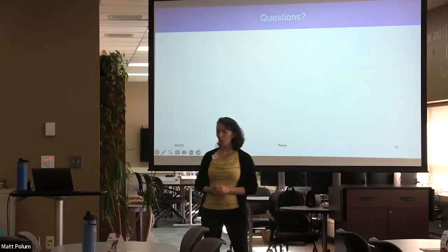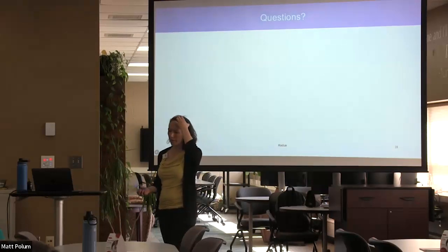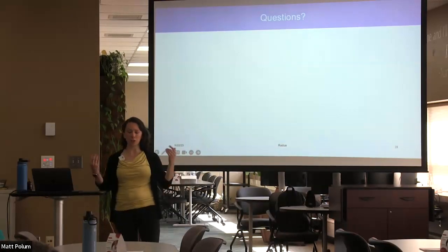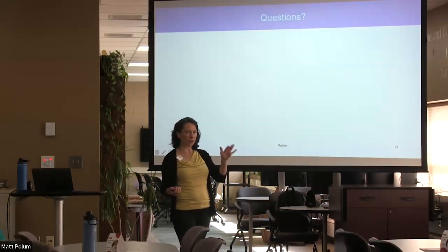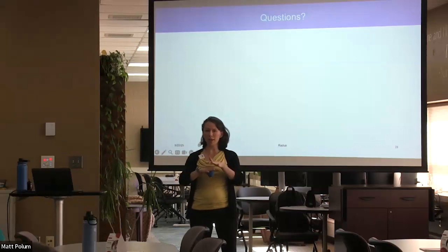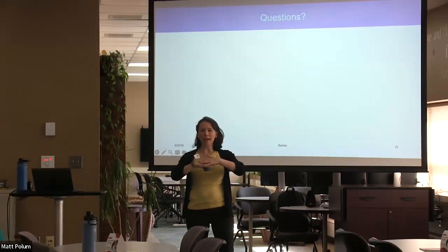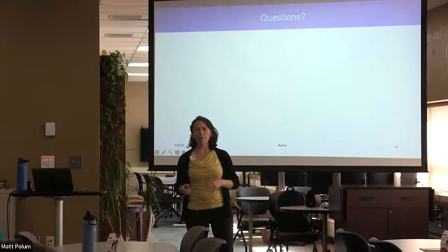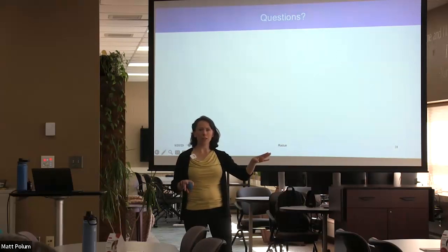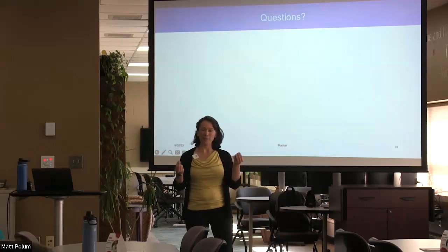So the question is, what is the geometry for these FTIR and Raman measurements? Am I reflecting off the surface, or am I passing through? And the reason why it's a great question is because we're dealing with very thin films that don't exist by themselves. They're deposited on a bigger glass substrate. So you can't just have one. And if I were to pass the signal through, I'd be picking up signal from my sample, but I'd also be picking up signal from my glass substrate. So I am reflecting off the surface for both, and I'm still picking up a little bit of the glass.